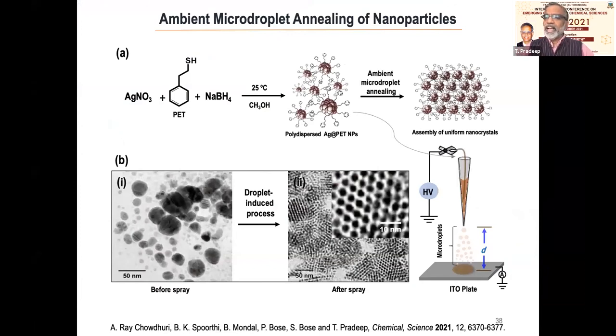So one thing that we do in our laboratory is make nanoparticles. But the moment you do chemical synthesis of nanoparticles, you get something called polydispersed nanoparticles. Nanoparticles are of all kinds of sizes. When you take these nanoparticles and put them through this droplet, exactly the same kind of synthesis that I told you about, we were surprised to see that these polydispersed particles become highly monodispersed. In fact, in some regions you can see particle order of this kind. And this is all happening at room temperature in air.